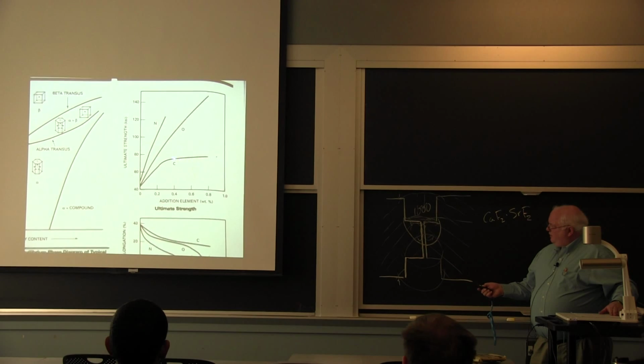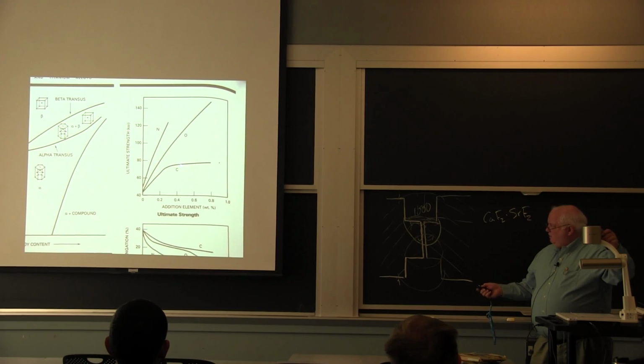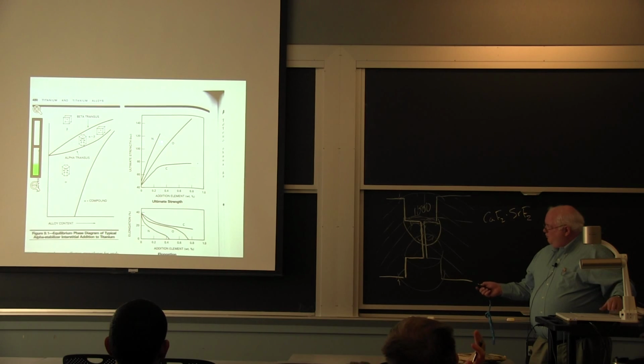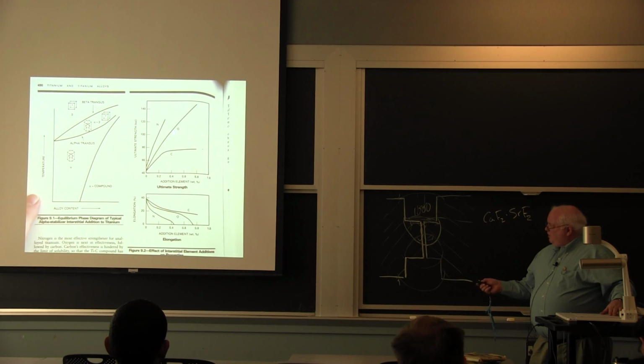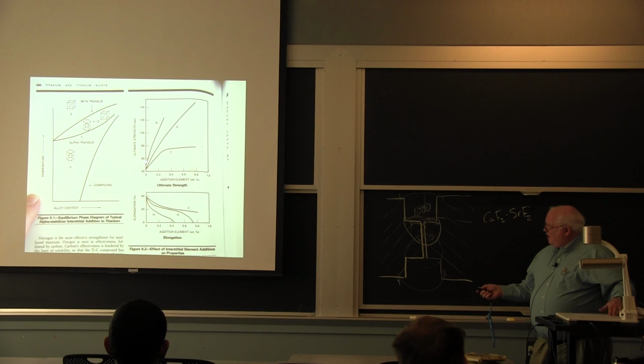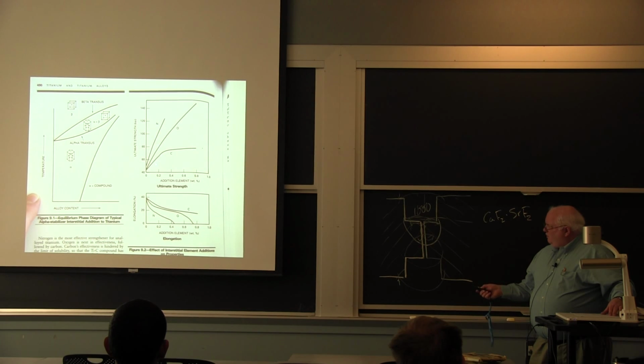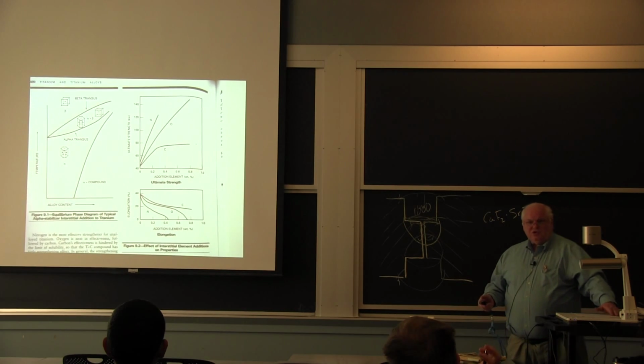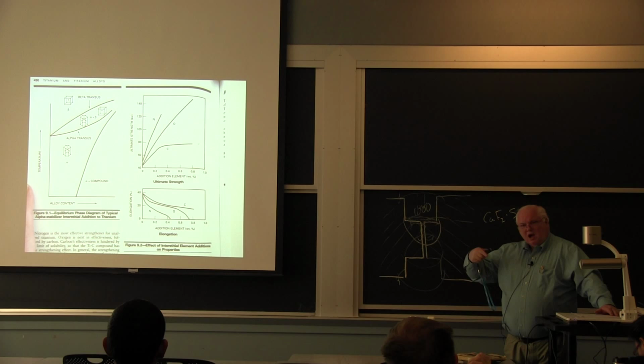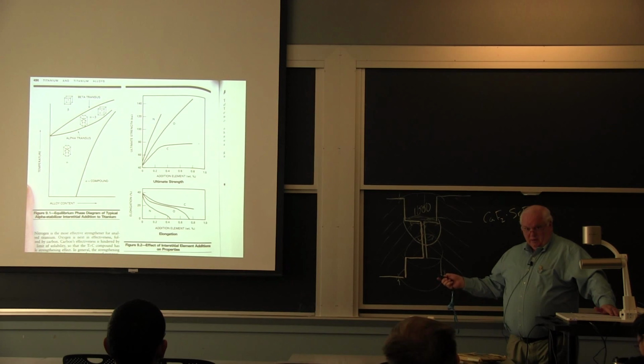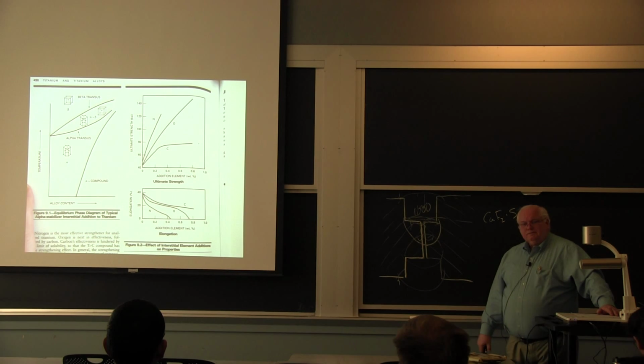But it turns out if you start looking at impurity elements, which is important in titanium, oxygen, nitrogen, and carbon, the strength goes up from about 40 ksi up to 100 ksi with 2,000 parts per million oxygen. The elongation goes down, but you can still have 10% or 15%, which is plenty of elongation in these alloys. So we actually add oxygen to strengthen titanium alloys, and we lose a little bit in elongation, but it's still got enough ductility.